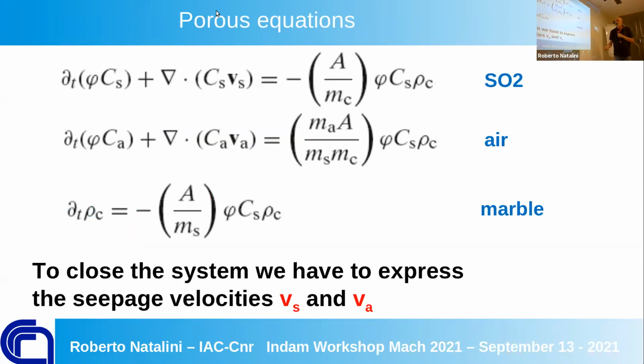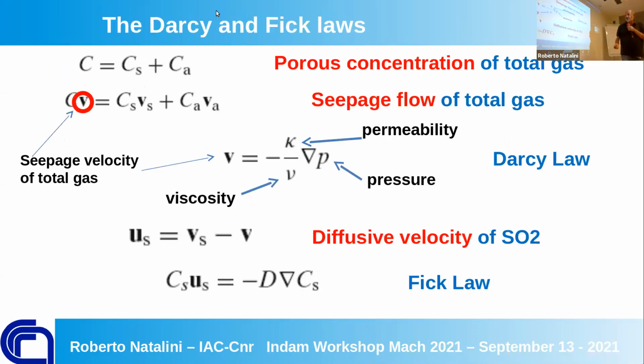So you can write down the equations, which say just that SO2 is flowing inside of the porous medium and reacting. Air is the same, but there is not a lot of reaction, and the marble is changing. You can eliminate the gypsum because, by the conservation of mass, the equation is already satisfied, and you can derive, thanks to two physical laws, Darcy's law and Fick's law, the equation for the seepage velocity, the total velocity of the fluid, and for the difference of velocity of the SO2 and the total velocity of the mixture. By Fick's law, you can address this kind of diffusive velocity, the movement of the molecules of SO2 inside of air. So we have this kind of equations.